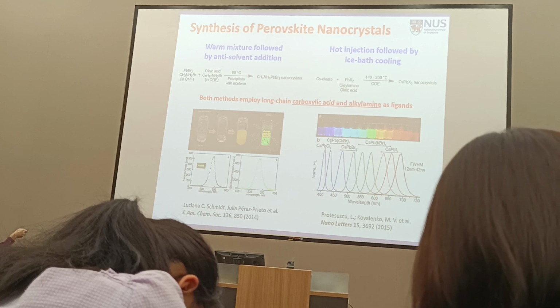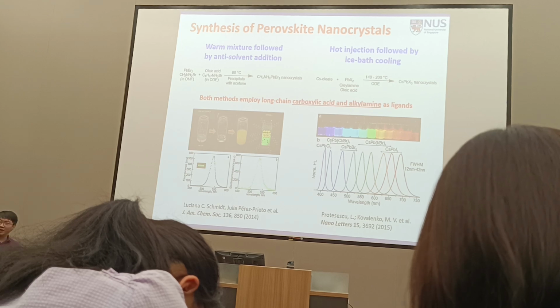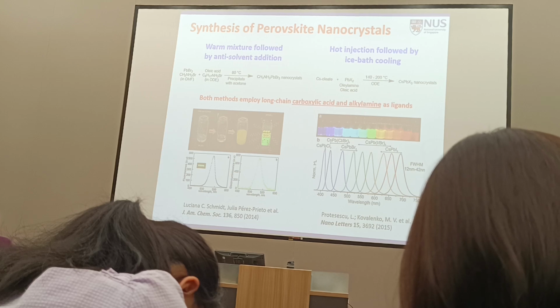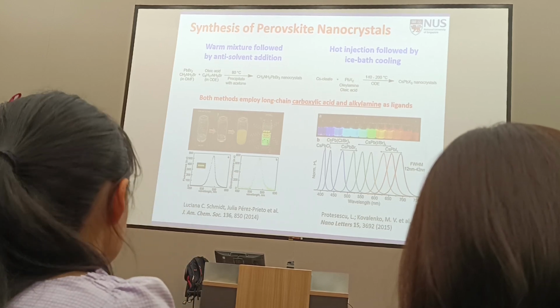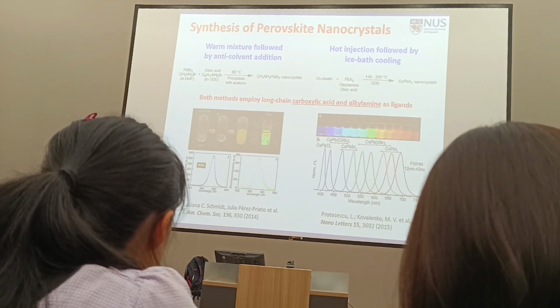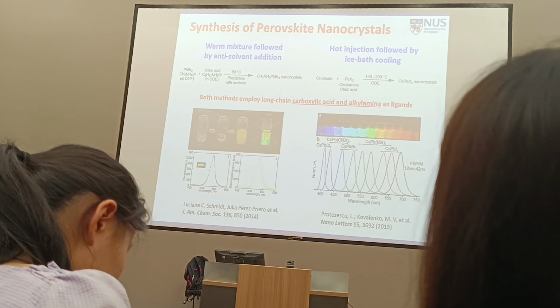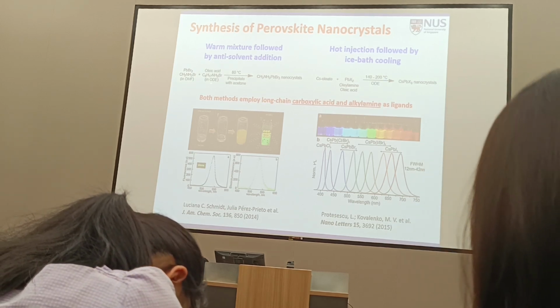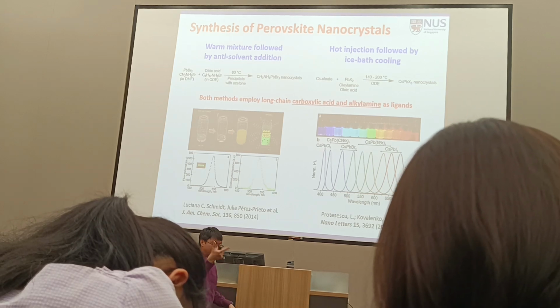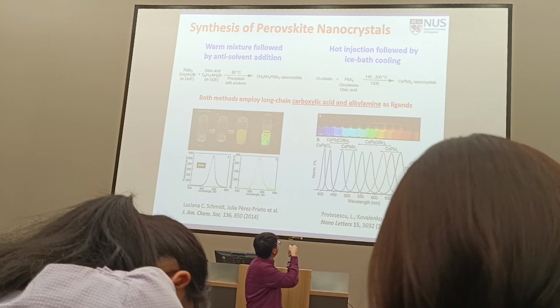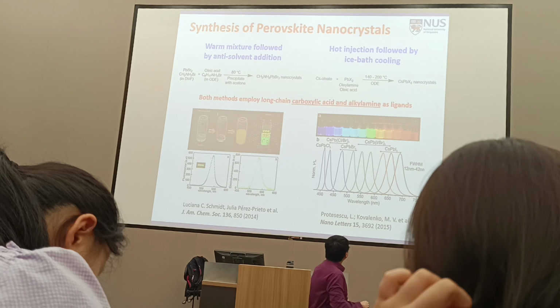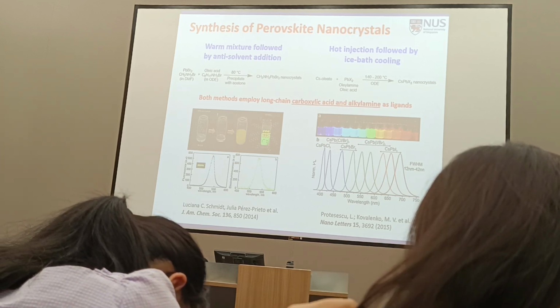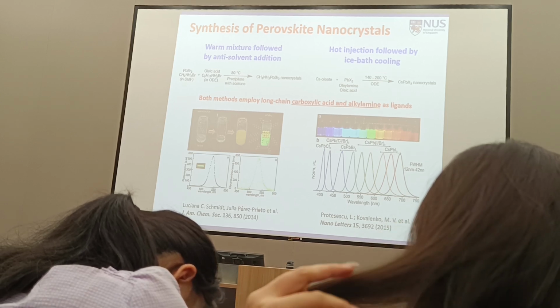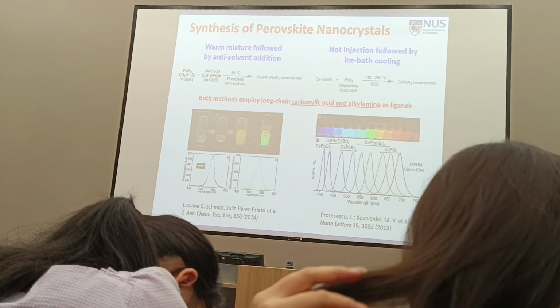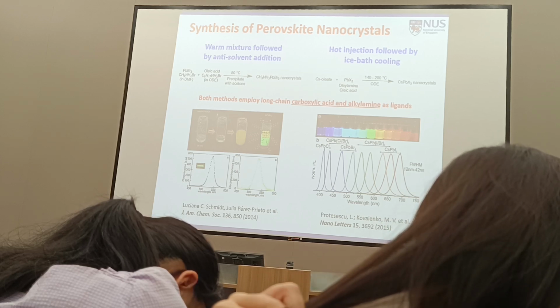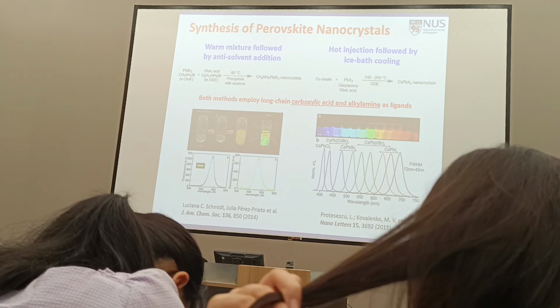So what they did was they used cesium oleate, so that contains cesium, and oleate is just oleic acid without the proton. So that's a ligand. They also used oleylamine, again a long chain hydrocarbon with amine at the end. So again, same concept: use an amine as a ligand, use acid as a ligand, use the cesium component, use a lead halide component. What they did was a hot injection. Hot injection means I mix them in a hot solution. Now, in this hot solution, these crystals grow into these colors.